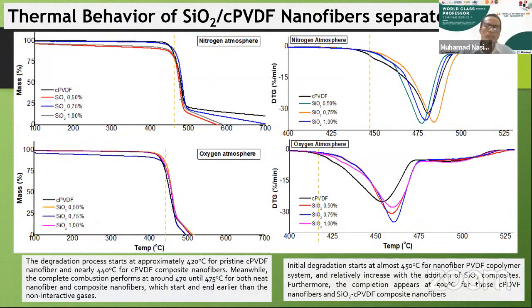And the important point is the thermal property of the silica co-PVDF nanofiber composite. We measured in nitrogen and oxygen atmosphere. You can see here that silica gives an effect on the thermal stability of the composite. You can see here the degradation temperature of the co-PVDF is around 420. But when we add silica to make the composite, the degradation temperature increases.